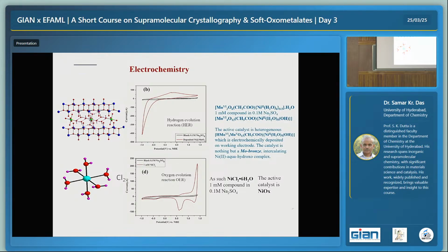Once it is encapsulated and intercalated in the MoO3, what compound you got, luckily this is also water soluble. I told you pH goes down. When you do CV, what did we find? Completely a miracle. The same species that gave water oxidation, here you get continuous hydrogen evolution. It doesn't give anything on the anodic side, it gives only hydrogen. We measured by GC-MS, it is hydrogen, for sure.